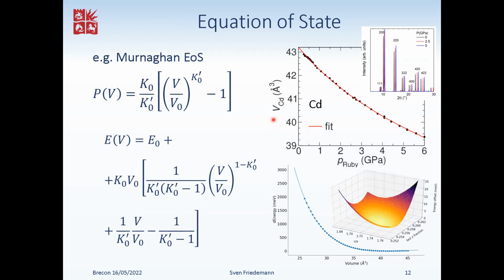I've made the case that the volume versus pressure is the energy density that we've got in the material. And hence, it's very interesting to look at the volume to get a starting point for how to understand materials. So here, for instance, is lattice volume versus pressure for cadmium, which you can infer from X-ray diffraction. Fitting this gives you compressibilities as well as the first derivative of the compressibilities. And you can do this both with experimental data as well as with DFT data, where you invert this essentially to be an equation of energy versus volume, and then pressure being the coefficients that dictate this fit.